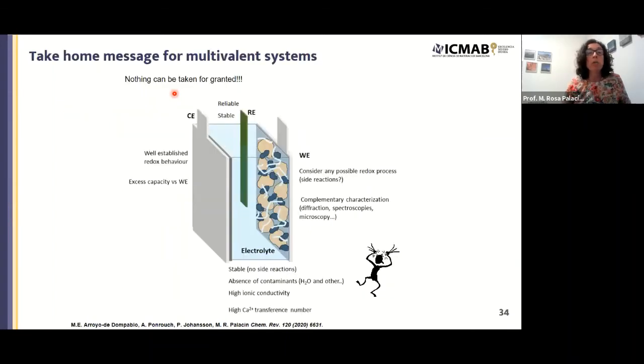So finally, just the take-home message for people interested in developing new battery chemistries in general and multivalent systems in particular is that nothing can be taken for granted. I mean, if you're coming from the lithium-ion battery field, you need to believe that nothing is reliable. Many side reactions can take place. You need to use counter electrodes that have a well-established redox behavior. You need to ensure that they have excess capacity versus the working electrode. You need to have a reliable reference electrode. There are many reactions that can involve the electrolyte that can give some electrochemical response, which you may mistake as coming from your electrode material.